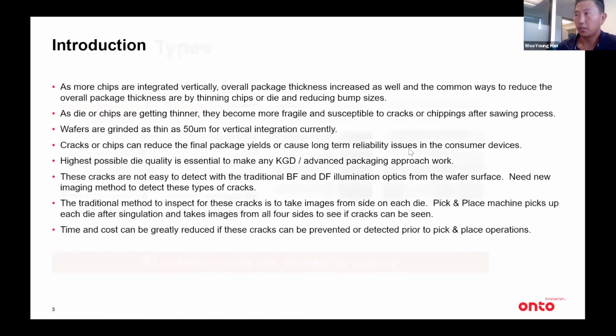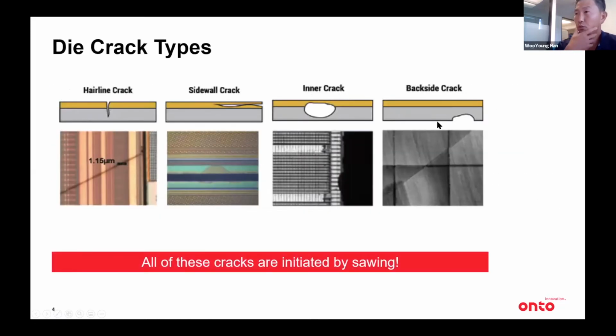Okay, so here I'm going to show some examples of typical crack types that we see in industry. The first one is what we call a hairline crack. This is a very fine hairline crack on the top surface of a die. This is what it typically looks like, and that's how it looks from the side. And this is what some customers call a sidewall crack, or sometimes peeling or delamination.